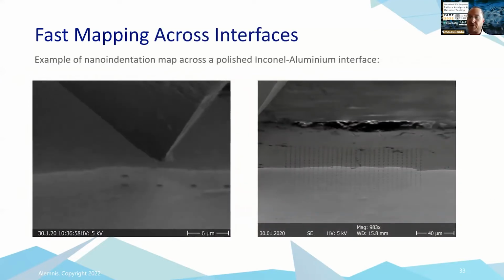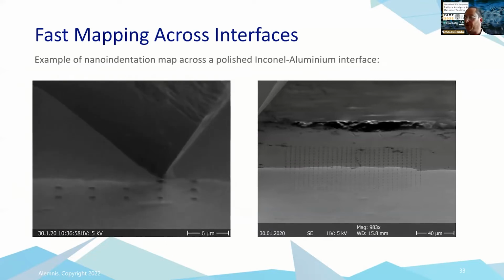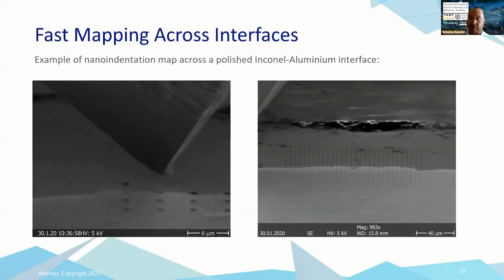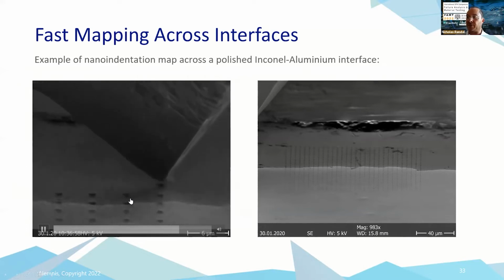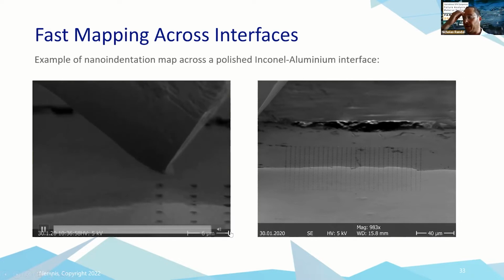We also use mapping to look at interfaces, of course, bonding lines, all types of different areas. This is actually the interface between two materials. So you can see the depth of our indents is constant, but we can see we're going into a softer material here because we've got more pileup around the indents. You can see the map to the right here.